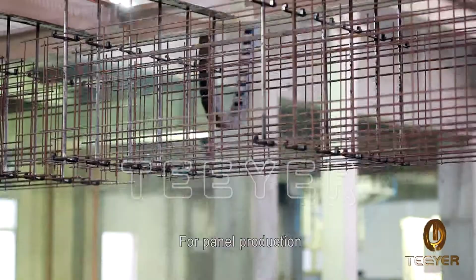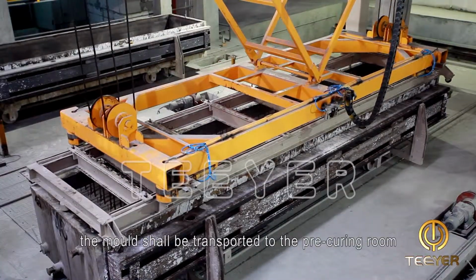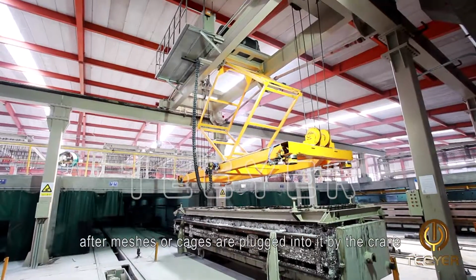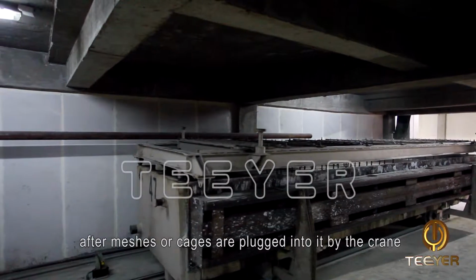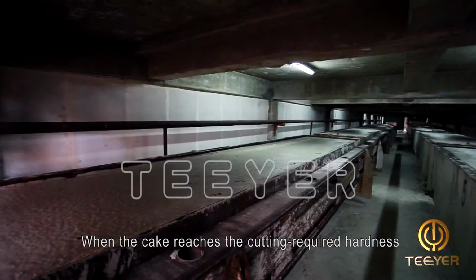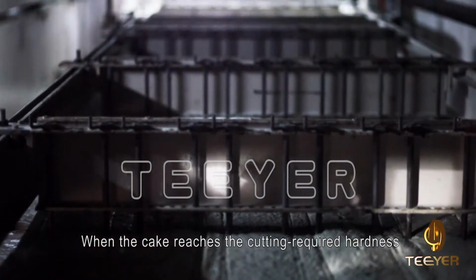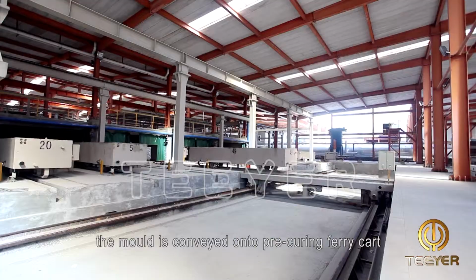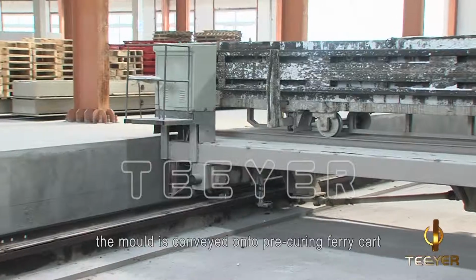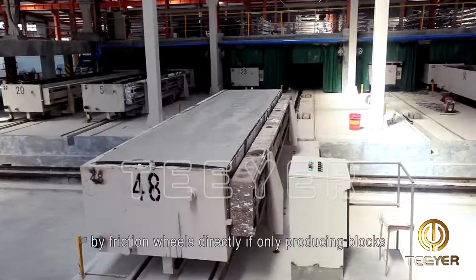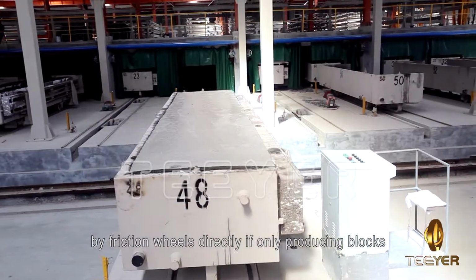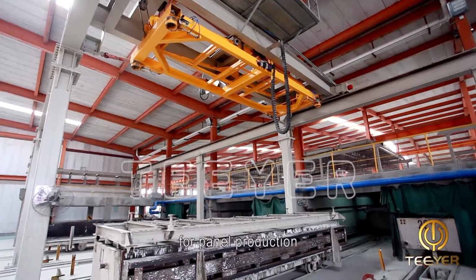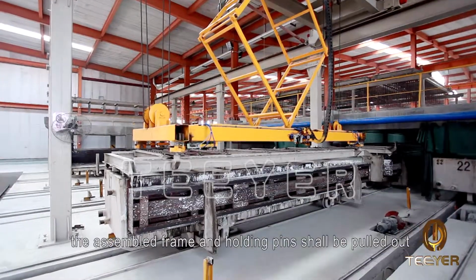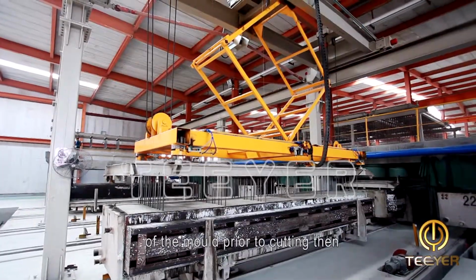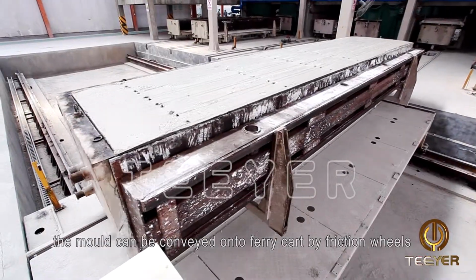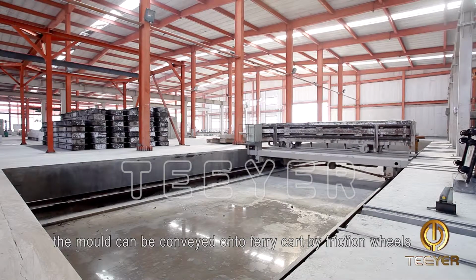For panel production, the mold shall be transported to the pre-curing room after meshes or cages are plugged into it by the crane. When the cake reaches the cutting required hardness after pre-curing, the mold is conveyed onto the pre-curing ferry cart by friction wheels directly if only producing blocks. For panel production, the assembled frame and holding pins shall be pulled out of the mold prior to cutting. Then the mold can be conveyed onto the ferry cart by friction wheels.